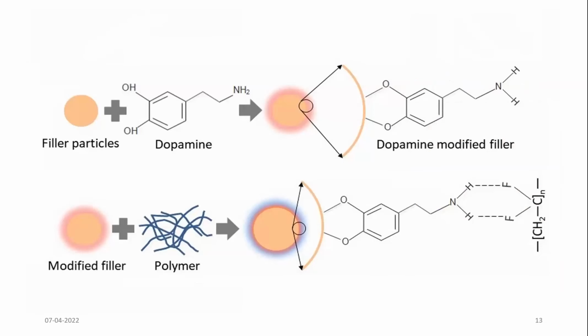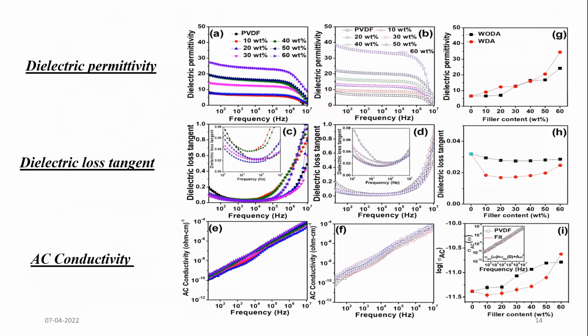So here you can see filler particles, then dopamine is added, then this is the dopamine modified filler, then this modified filler was added with polymer, and this is the structural diagram of the final filler which was cast further. Now these are dielectric permittivity, dielectric loss tangent, and AC conductivity results. In each result, it was seen that dopamine added filler gave better results and a better beta phase.